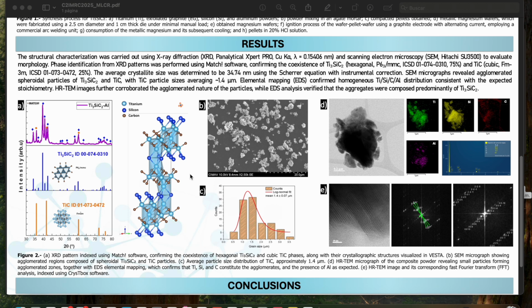The microstructure supports the coexistence of nanocrystalline MAX with micron-scale carbide. SEM reveals agglomerated, roughly spheroidal particles, with TiC centered near 1.4 micrometers in size. HRTEM shows fine agglomerates, and FFT indexing matches the assigned phases. EDS mapping indicates homogeneous distributions of Ti, Si, C, and detectable Al within the aggregates, in line with the intended